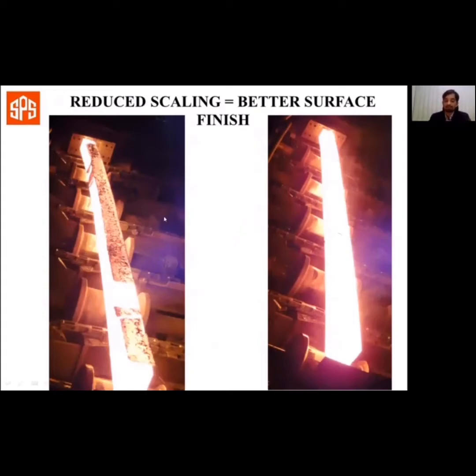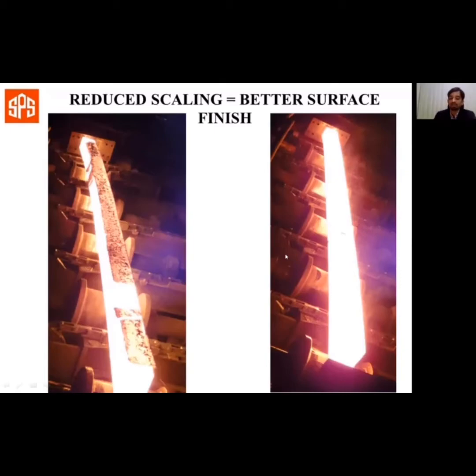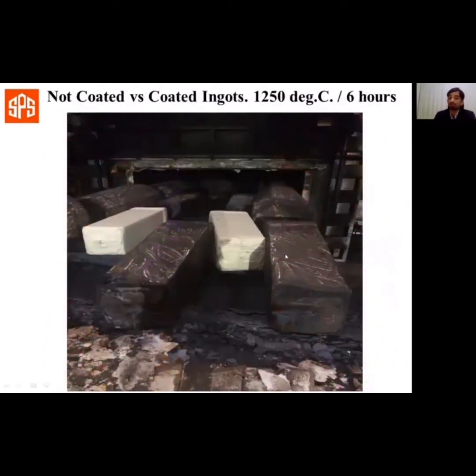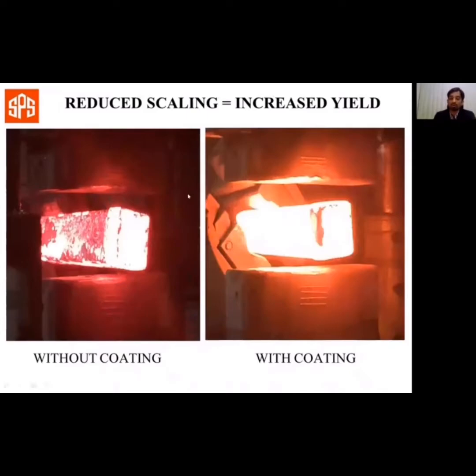And the result here, on the left is a not coated billet with sticky scale, as you can see. On the right is the ESPON coated billet that shows very less scale. In expensive grades of steel, it helps even if scaling is reduced by 50%. These are stainless steel ingots coated with the sole aim of reducing scale loss and increasing yield. Again, the comparison between not coated versus coated ingots after heating are visibly remarkable even before measuring the scale thickness.